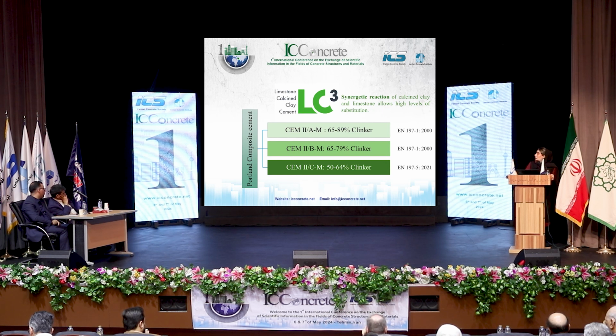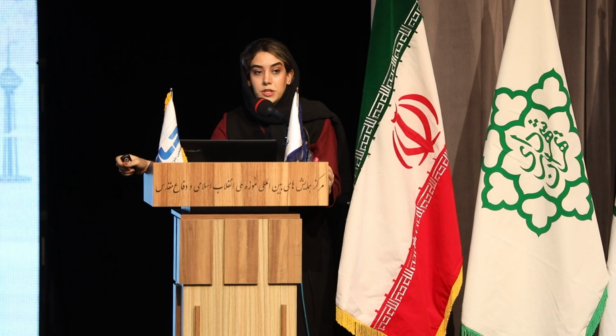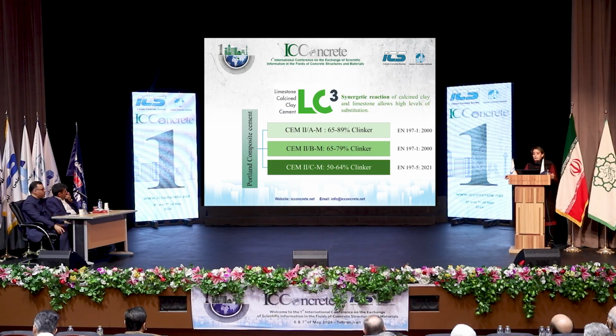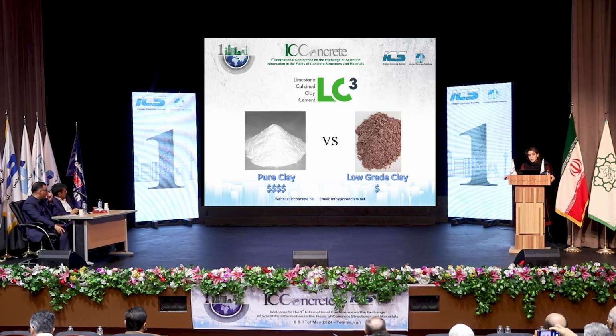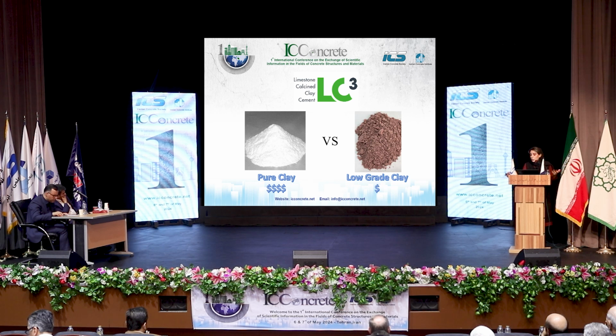You can see here that in LC3, until 2000, we have just standards with clinker replacement of around 20 to 30%. But in 2021, the clinker factor was introduced as 50 to 65%. One of the benefits of this LC3 system is that we don't need to use very pure clay. With low grade or moderate grade clay, we can reach LC3 with proper properties and good permeability properties.